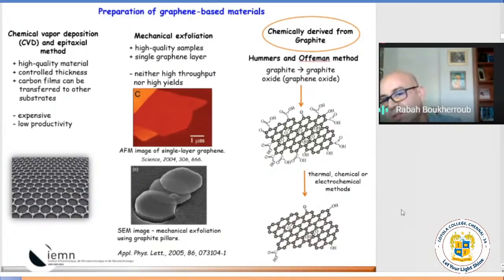This starts from graphite, which is a natural material, and you just oxidize it, and you lose all the properties of graphene when you oxidize. Graphene oxide is really an insulating material, it's not conducting. It becomes completely different from what you call really graphene. So you have to remove all these oxygen functionalities to recover the graphene type material. But of course, that's not always as simple, and there's also always a confusion in naming.